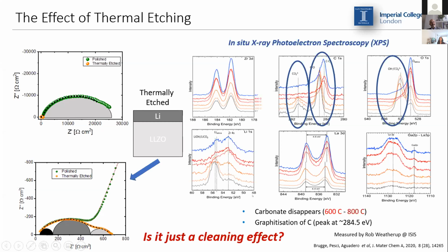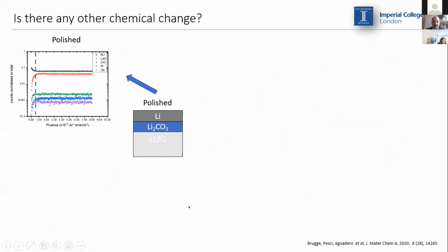So the question that arose now was, is this just a cleaning effect or is there something else going on? To answer that, we did some SIMS on the polished samples. From the SIMS depth profile, we see an initial surface region which appears to be enriched in lithium but depleted in all the other garnet components. This seems to confirm that we are looking at a lithium-rich layer, which could be either lithium carbonate or lithium hydroxide, on top of our samples.